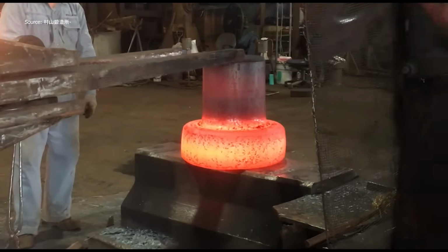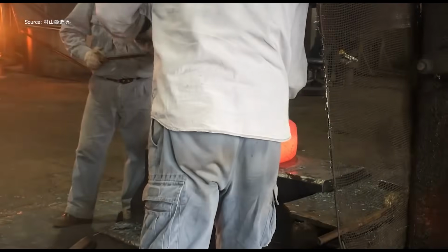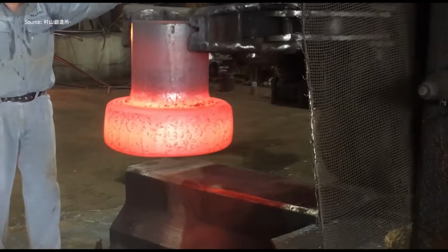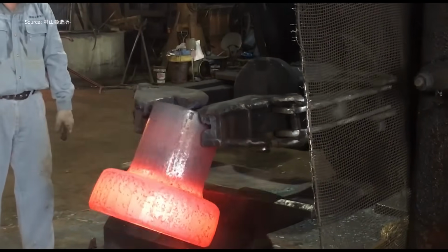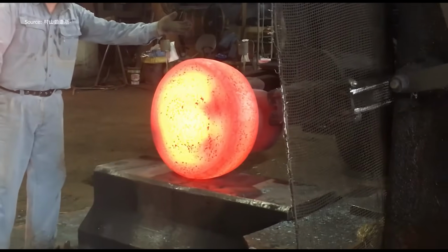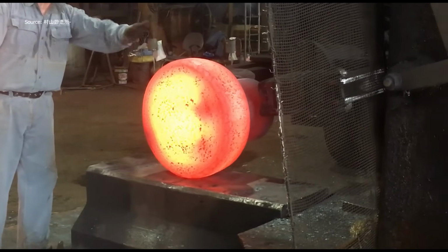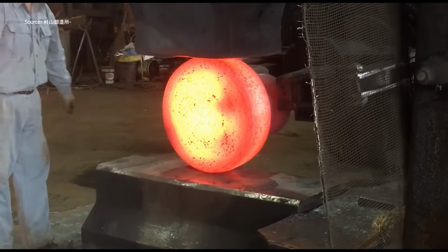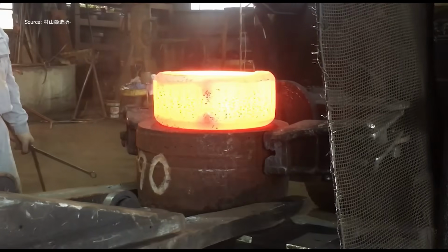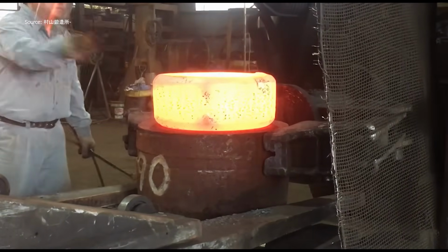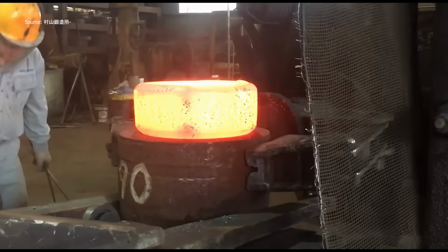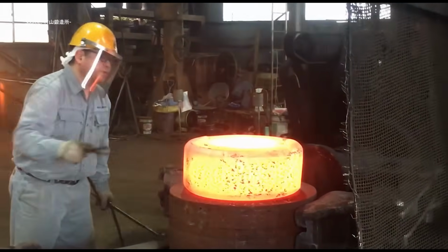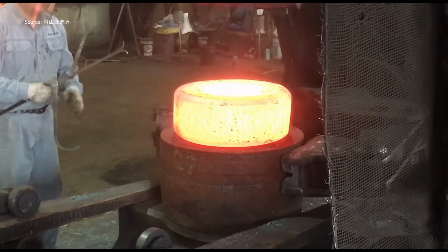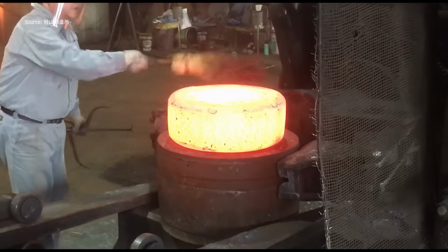Too cold and the steel cracks. Too hot and the structure weakens. As the forging nears final dimensions, blows are lighter, more precise. At 900 kilograms, this coupling isn't just big, it's precise. Workers rotate it between strikes to ensure even pressure distribution. Sparks fly, the forge roars. But the result is quiet beauty in steel.